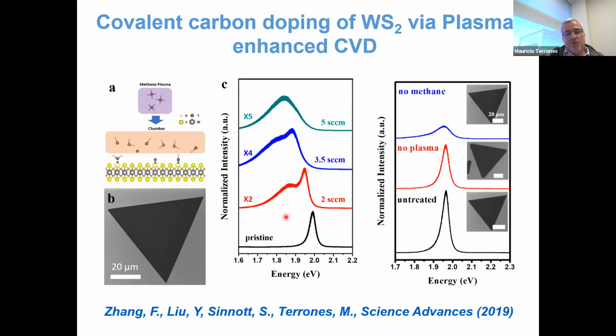Just to show you what happens, if we don't put in any methane, you don't see these shifts. This is an untreated sample. This is just by heating it, and there's no plasma. You just heat the sample, nothing happens. If you use the plasma with argon and no methane, then this is what happens, but you don't see this behavior of the peaks. So again, this is something that we tried to confirm.